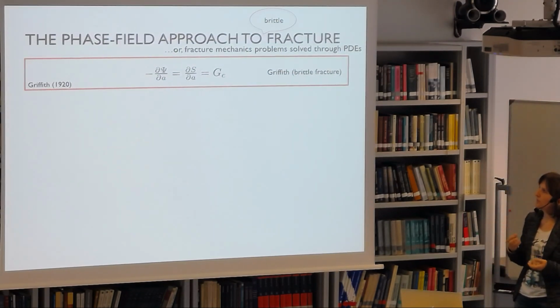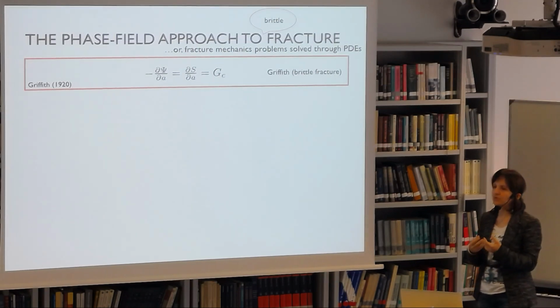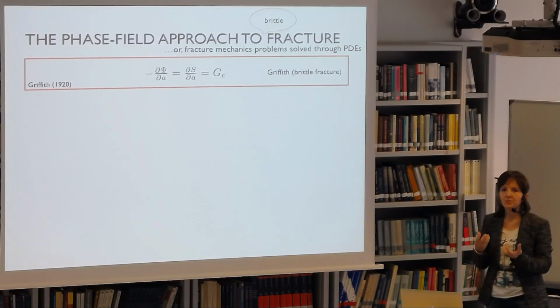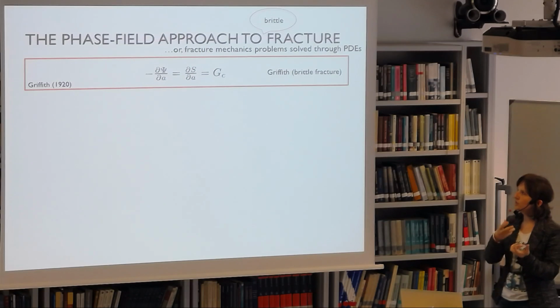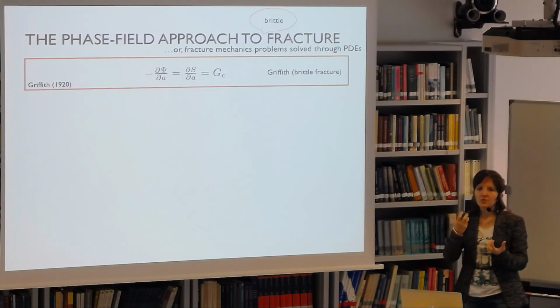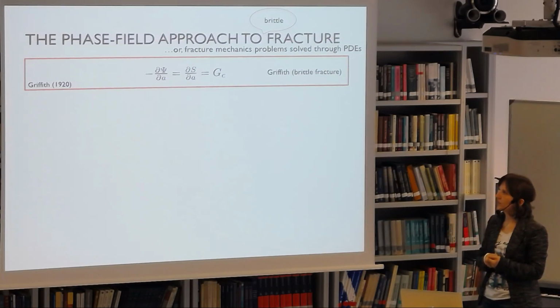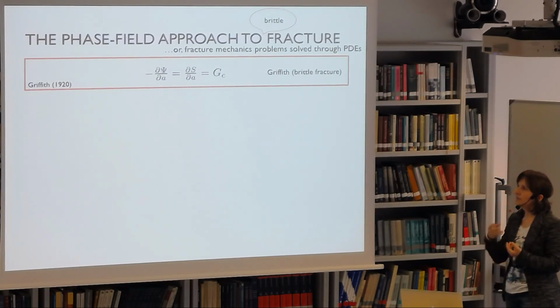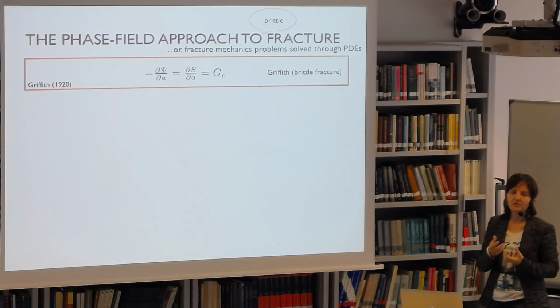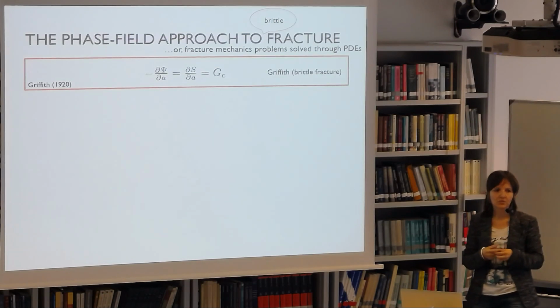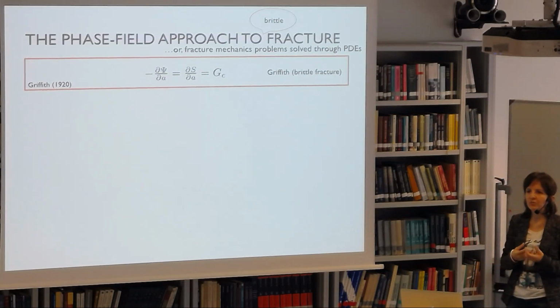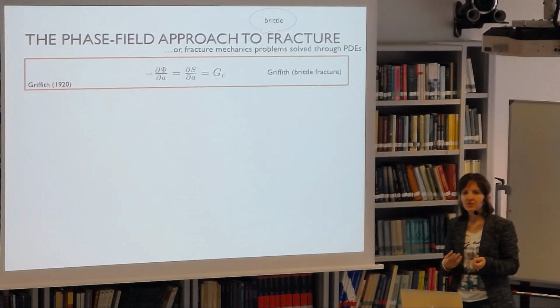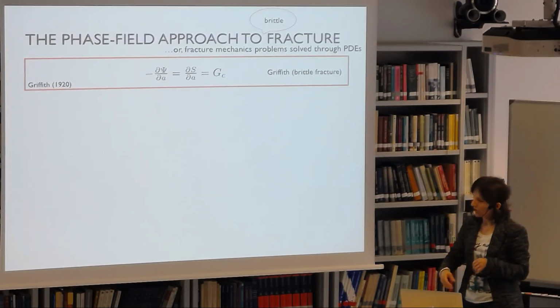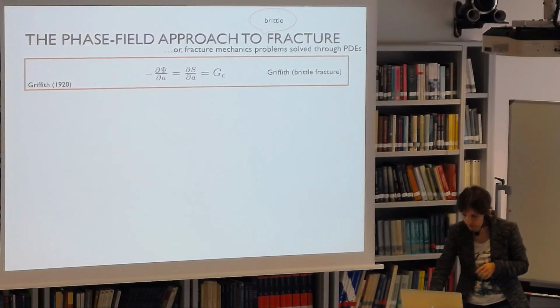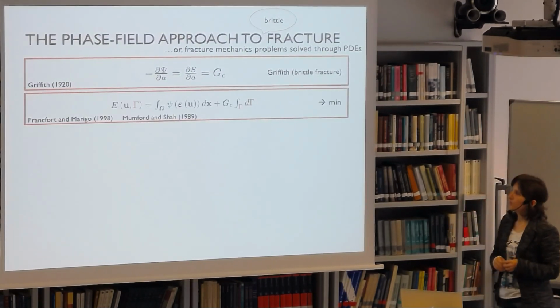So what Griffith is saying is that the propagation is possible when the so-called critical conditions are met, when the release of elastic energy due to dA is equal to the supply of surface energy needed for this dA. And this supply of surface energy per unit length in 2D or surface in 3D of the crack is what we postulate to be a material property that we call GC, so the fracture toughness of the material, or the critical energy release rate, or the fracture energy, or so forth. Different books or papers use different terminology.